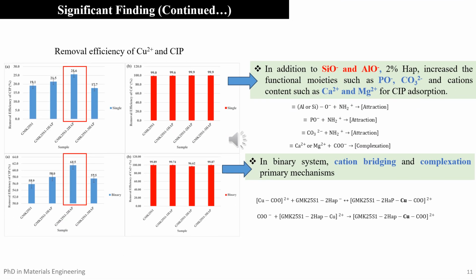Now let's look into the removal efficiency of copper and ciprofloxacin in both single and binary system. The removal efficiency of ciprofloxacin first increased with increasing hydroxyapatite particle up to 2%, while this was further improved in the binary system due to the cation bridging effect and complexation. However, the removal efficiency of copper remained the same as it was not affected by the hydroxyapatite particles.